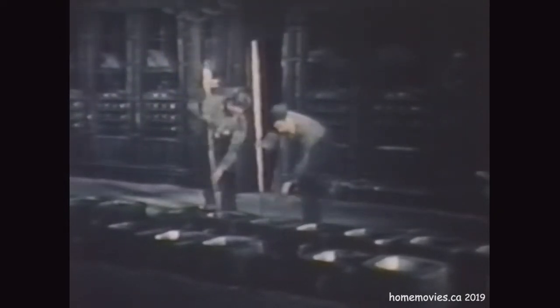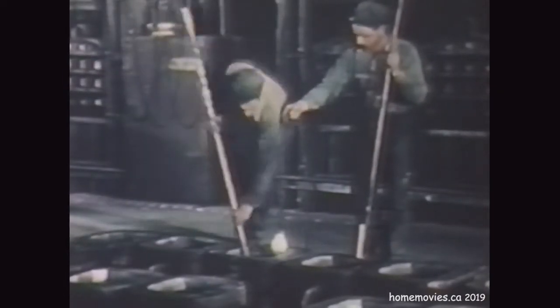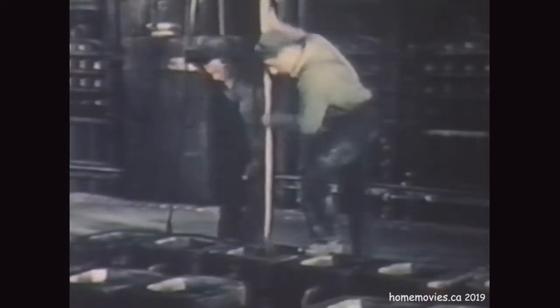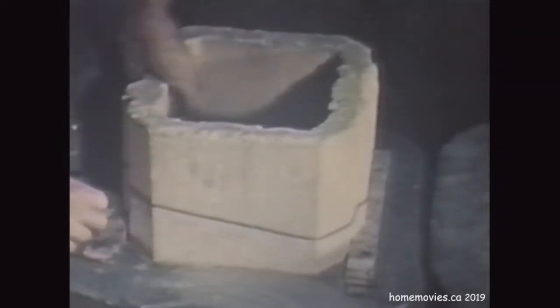Far in advance, the ingot molds are prepared to receive the molten steel. A thorough cleaning and brushing prepares the molds. A fine coating is sprayed inside. Great care is taken with the molds, for it is here that sound, homogeneous steel is born. A plug goes in, and a refractory hot top fits above, a reservoir to feed the ingot as it solidifies and shrinks.